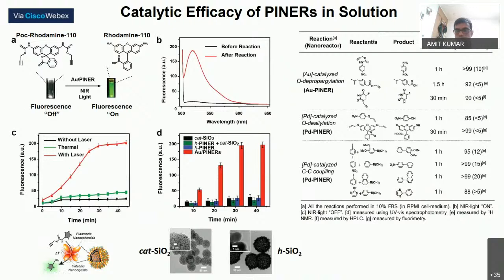We also measured the catalytic efficacy of the nanoreactors, because we wanted to test them in the cells. Before that, we tested them for the conversion of POC protected rhodamine 110 into free rhodamine 110, which is a gold catalyzed reaction. The gold coordinates with the alkyne part and performs this deprotection chemistry. We saw that within 30 minutes of laser irradiation, at around 300 milliwatt per centimeter square laser power, we could complete almost quantitative conversion.